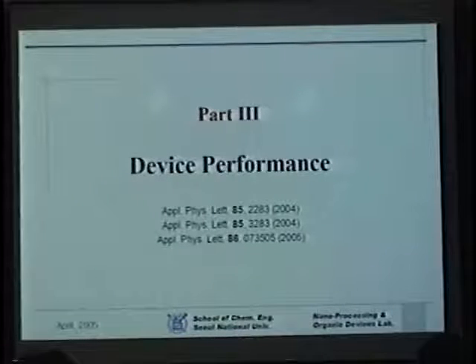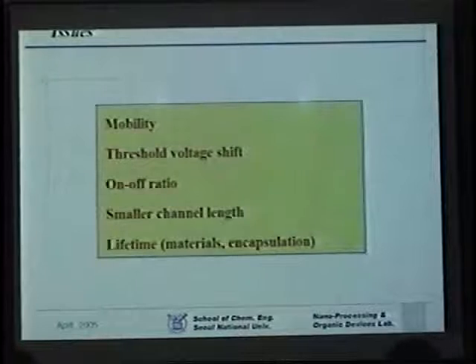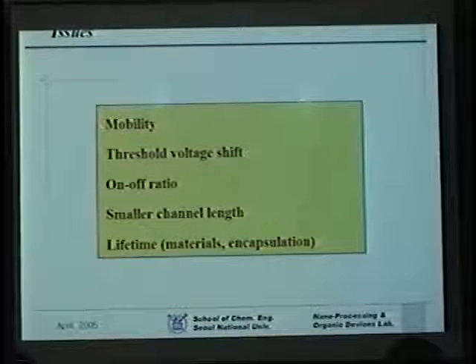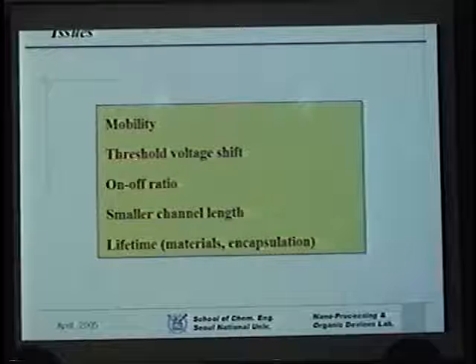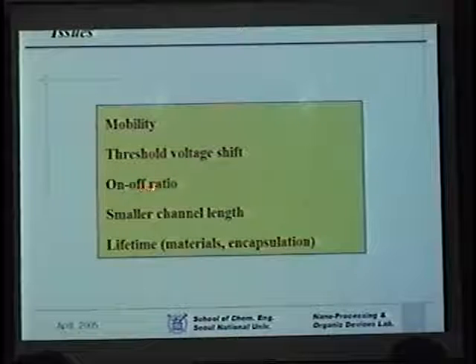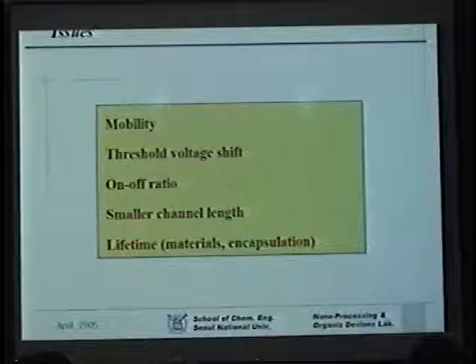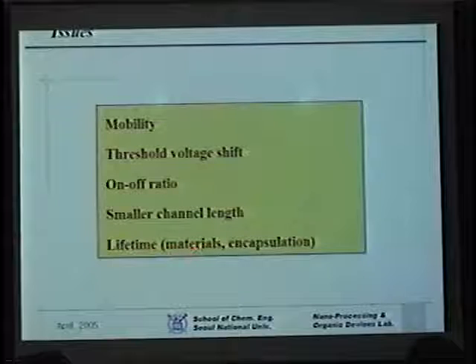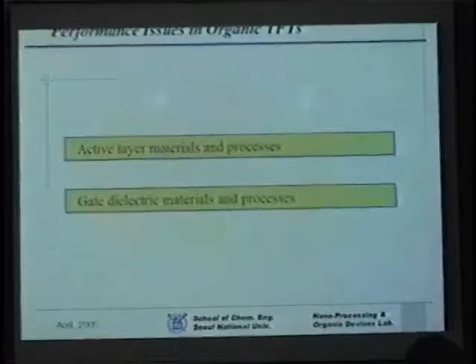Which brings me to the last subject, which is device performance. And the issue here, of course, always is mobility, because in organic devices, the mobility is very low compared to silicon devices. And when you use organic substance, there's always a shift in threshold voltage, and so there's a need to control this. Another concern has to do with the on-off ratio, which tends to be very low compared to silicon devices. And there's an issue about the channel length, which in a way determines the device characteristics as well as the number of devices you can jam into a given area. And of course, when it comes to organic material, there are always lifetime issues, which are related to materials and encapsulation.